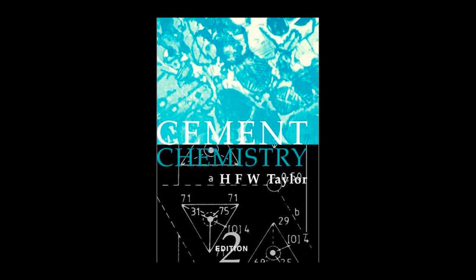Okay, so the chemistry has been successfully formed at 1450 degrees. Now we get to the cooling stage, the quench effect, and this introduces defects that can either save the product or completely ruin it. The cooling rate is absolutely pivotal because, as we've established, cement phases are rarely in true thermodynamic equilibrium. Non-equilibrium cooling immediately creates these microstructural features like chemical zoning in the ferrite crystals. Zoning meaning the chemical composition is not uniform across the crystal itself.